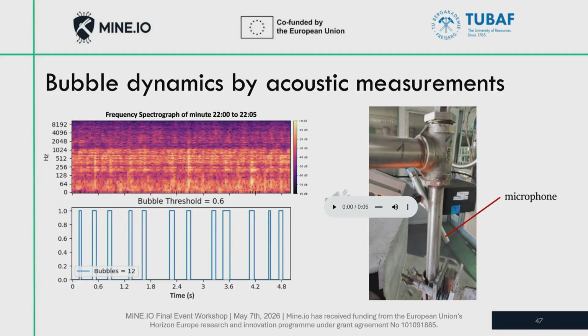Coming to the bubble acoustic measurements for a moment, you can see here a very nice frequency spectrogram, where we can extract the individual bubbles of our system. This depends very much on viscosity, temperature and composition of the slag system, and therefore is a very nice tool to determine if it's very fluent, or if it maybe starts to freeze in, then it stops bubbling because it's just blowing, not liquid anymore. Very dangerous also.